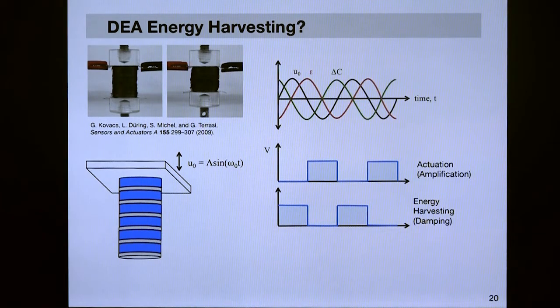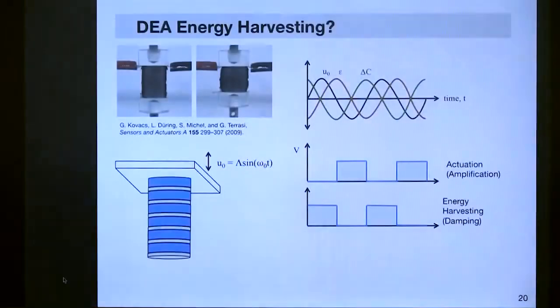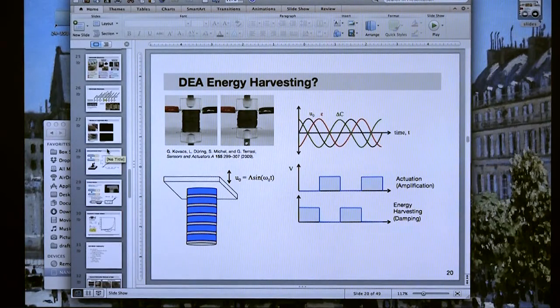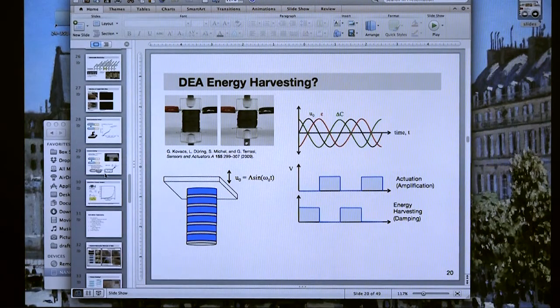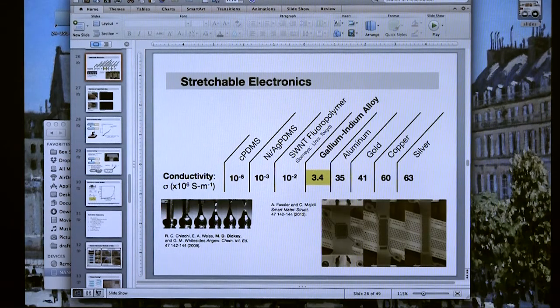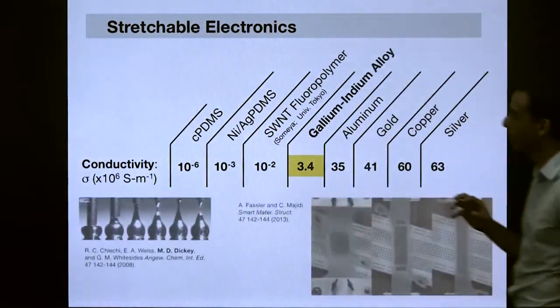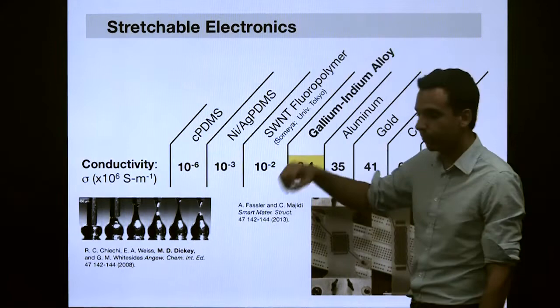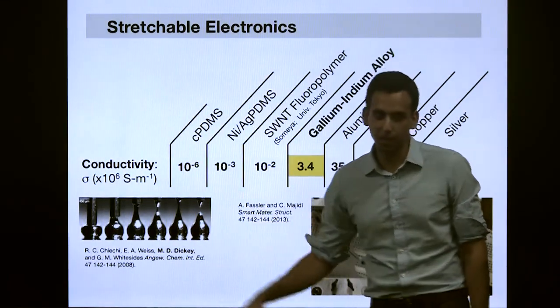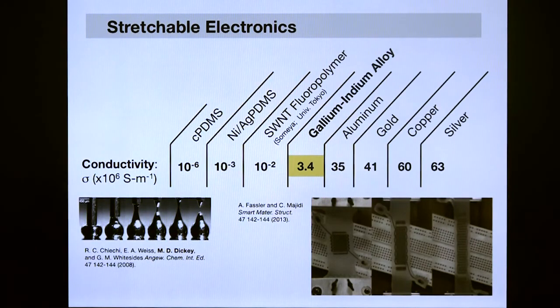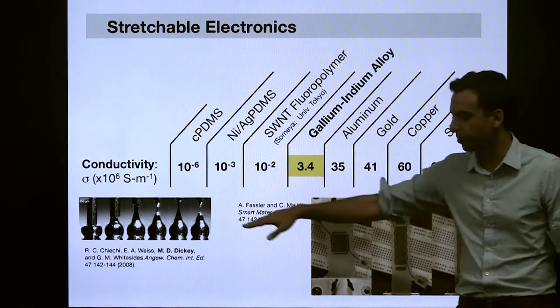When you laser pattern your EGaIn, what prevents it from flowing out of the channels? Is it frozen? It's the surface tension. Surface tension. In fact, I wouldn't even say it's surface tension. I didn't talk about this, but you can see it in this picture here. The liquid metal forms this gallium oxide skin, and that allows it to hold its shape. That's the essential property where liquid metal is unique in being laser patternable using that vapor recoil force from the PDMS. Because of this gallium oxide skin, it holds the liquid in place inside the channels and prevents it from spilling out.